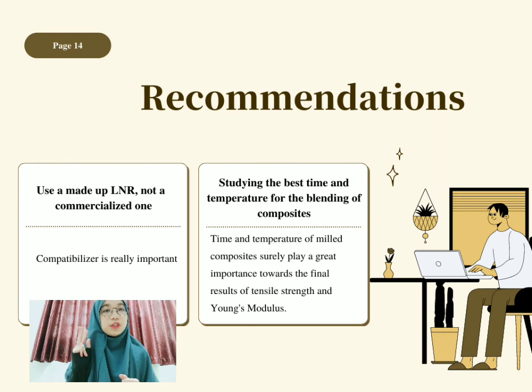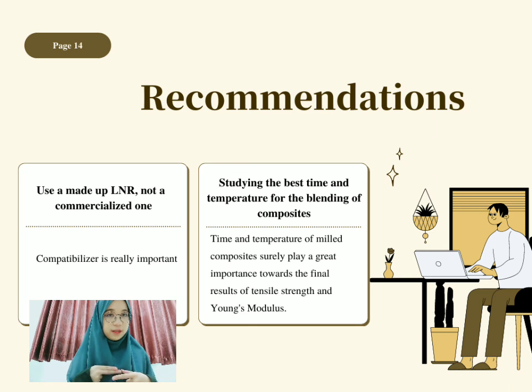So actually there are two recommendations that I will suggest in this study. First, we should use a self-made liquid natural rubber, not a commercialized one, as the compatibilizer is really important to decide the final results of the study. The second one is we need to study the best time and temperature for the blending of composites, as the time and temperature of milling composites surely play a great importance to the final results of tensile strength and also the modulus. So that's all from me.